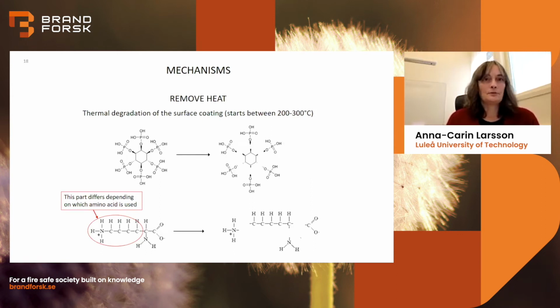So with all this information, we can now explain what exactly is happening step by step with our flame retardant. The first thing that happens between 200 and 300 degrees is that this heat will thermally degrade our flame retardant surface coating. So we will then remove heat because it's needed for this degrading. The phytic acid will form phosphate groups and this cyclic carbon ring. The amino acid, depending on which amino acid we have, different types of decomposition products can form. But one thing that is common for all amino acids is that we get CO2 and ammonia.